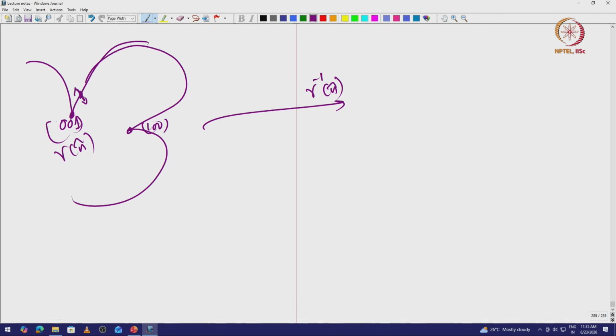So, this huge cusp here becomes a huge spike, and here also it becomes a huge spike like this, right. And now I am going to say that look, I am actually looking at some surface which is at a small deviation, and that small deviation is here, right. And because of the spiky nature, when I do this nice line-like construction, the only point that becomes stable is this 1 0 0 point, right. So, there is no region of stability.